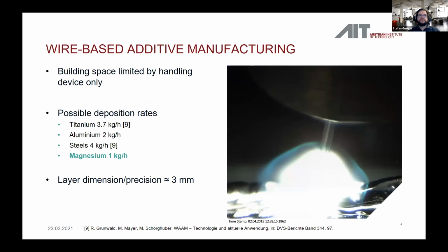So the building space is limited by the handling device only, and deposition rates for magnesium can be up to 1 kilogram per hour, and in the meanwhile above this. As this process is capable of high production rates, the aim for process development is also to increase these deposition rates. And the layer dimension or the precision is dependent on the wire diameter. So it's typically about 2 to 5 times the wire diameter you use. So 3 millimeter can be achievable with a 1.2 or even a 1.6 millimeter diameter wire.